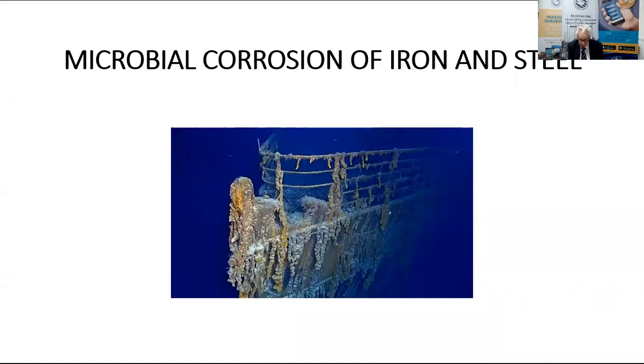The bacteria are autotrophic, acidophilic, short, non-sporulating rods, approximately 0.5 to 1.5 micrometers in size. They occur as single cells or in pairs and are mobile. The optimum temperature for growth is about 25 to 30 degrees C, but they die at temperatures above about 55 to 60. They are colourless, rod-shaped, gram-negative bacteria and have polar flagella. They possess an iron oxidase which allows them to metabolize metal ions such as ferrous iron. They are strictly aerobic bacteria, and all species are respiratory organisms and are obligate autotrophic organisms.